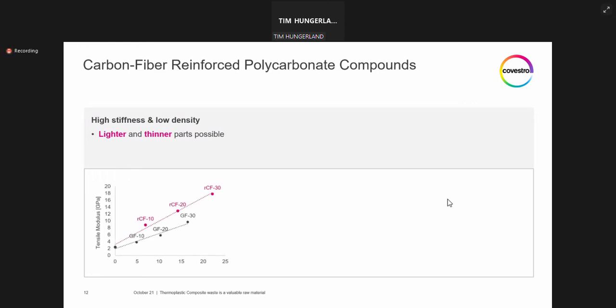So first and foremost, the clear advantage of carbon fiber is, of course, its high intrinsic stiffness and significantly lower density compared to, for example, glass fibers. With these attributes, carbon fiber reinforced thermoplastics allow for the design of lighter and thinner parts. In the first graph, you can see product stiffness based on the contained fiber volume when comparing carbon and glass fiber. At the same fiber content, carbon fiber reinforced thermoplastics reach a much higher tensile modulus than with glass fibers. Or if you want to look at it from a different perspective, parts with a certain stiffness target can be realized with less fibers when switching from glass to carbon.